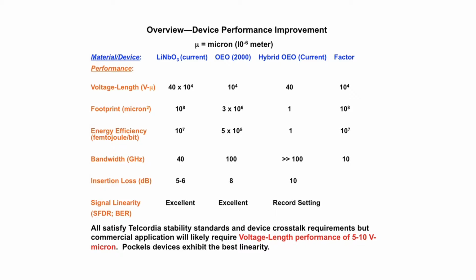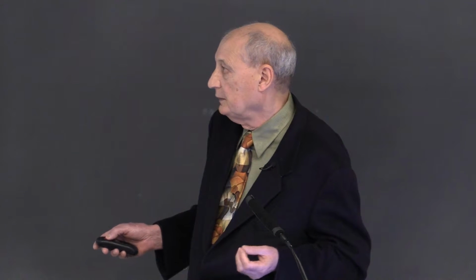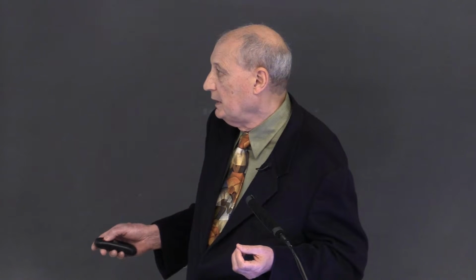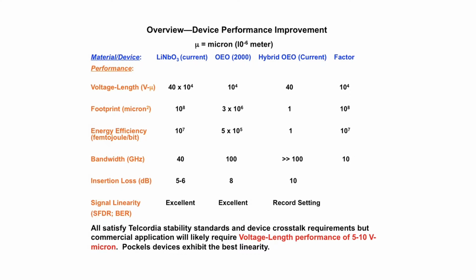Insertion loss is the one, by the way, I might note that that silicon injection modulator has terrible bandwidth, worse than lithium niobate. The parameter that lithium niobate excels on is insertion loss, because it's a very transparent material. But I would note that insertion loss depends on device length, which in turn depends upon electro-optic activity. Hence, as electro-optic activity is improved in organic electro-optic hybrid devices, this value will drop down.